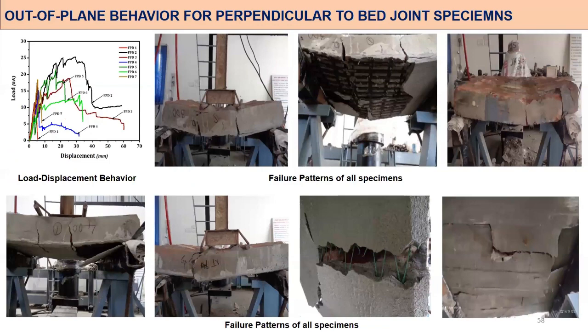You can see the graph. It's wonderful, right? Basically, the conventional one has gone up and come down. But with reference to the strength of the grid, I can get a wonderful post-peak behavior and gradual degradation. So what does it mean? I can see the vertical crack here, and my brick sample has a wonderful amount of deformation. So this can be an efficient stress transfer mechanism of the textile which we have used in the masonry.